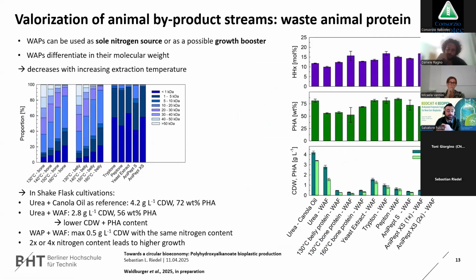So then some new work my students put together is that we are looking to use waste animal proteins as a replacement for conventional nitrogen sources. But as we see here, protein hydrolysates are not completely hydrolyzed to amino acids, so we have longer molecules, and we made an analysis to see the different molecular weights. What we saw first is that the cells might not be able to utilize all of the longer fractions, and therefore we got a little bit less PHA or cell weight from these shake flask experiments. So there's room for optimization, but at least it should work.